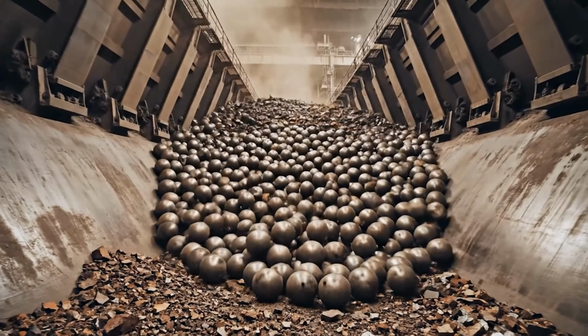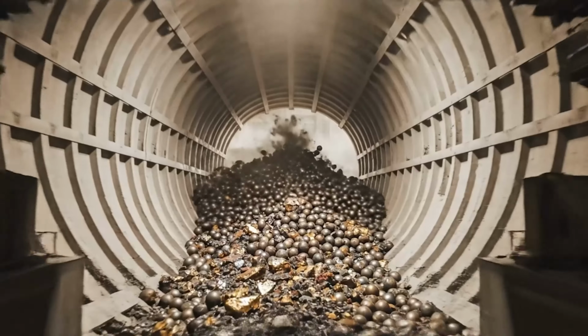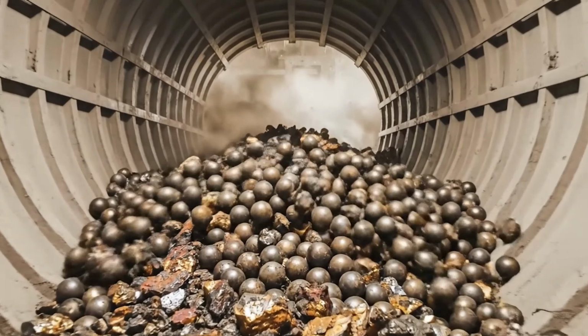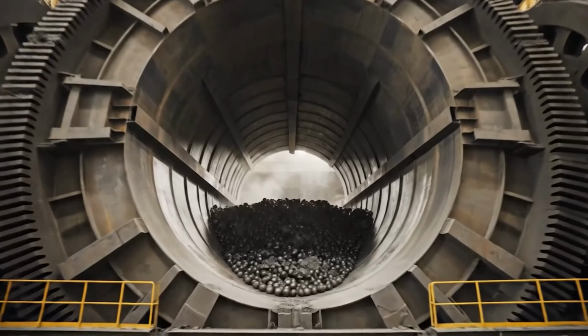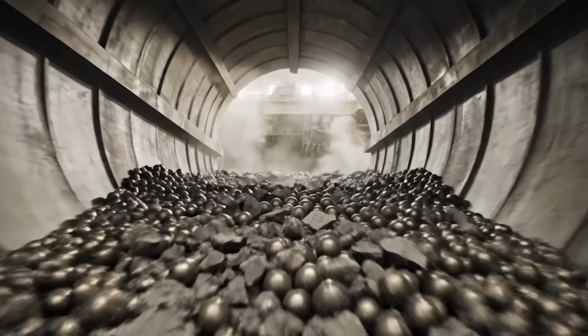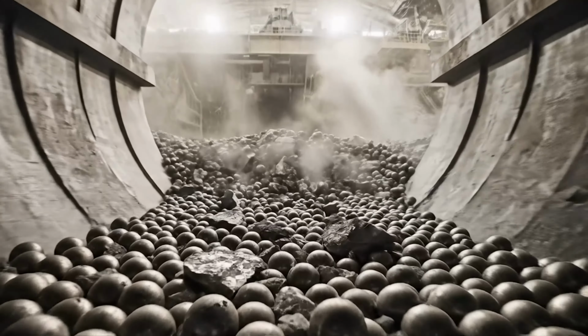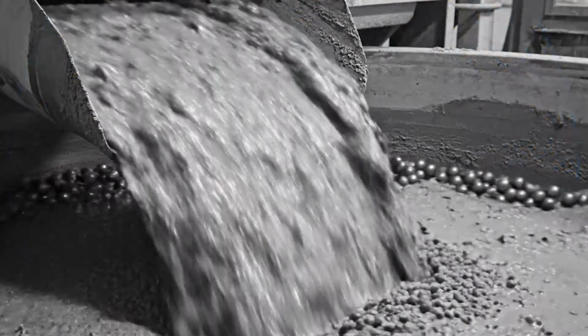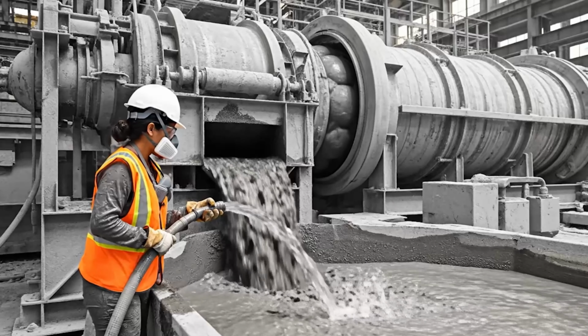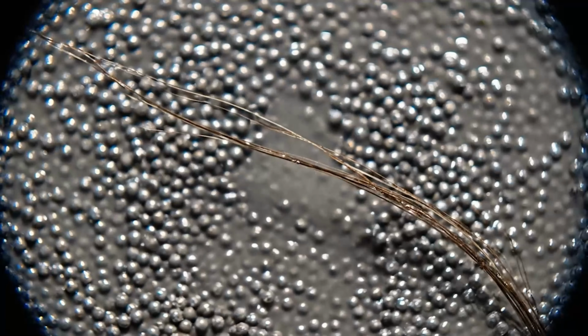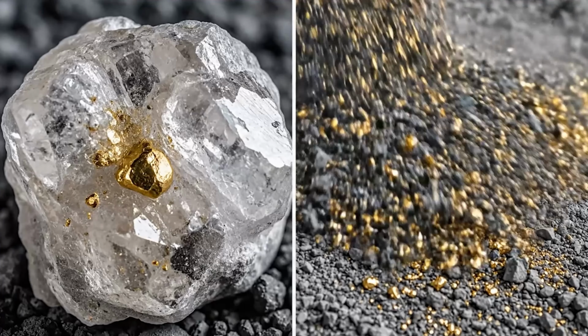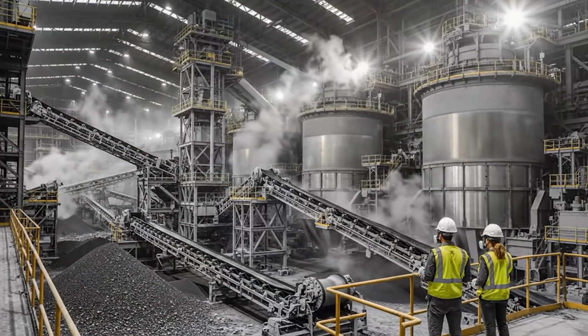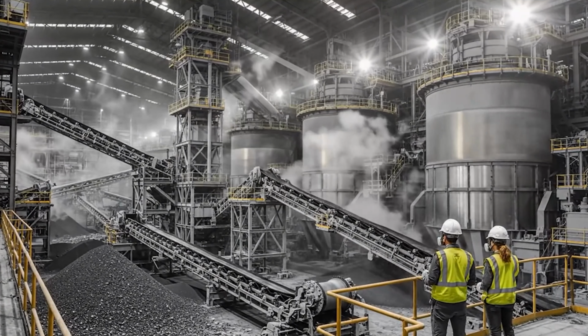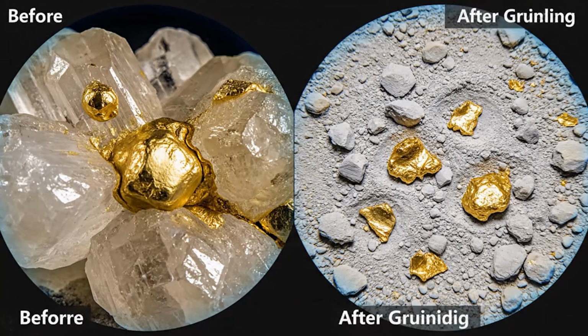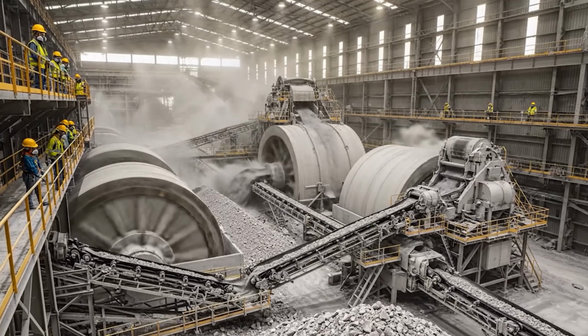The ore goes into semi-autogenous grinding, SAG, mills. Enormous rotating drums up to 12 meters in diameter, lined with steel and partially filled with the ore itself plus steel balls. Water is added to make a slurry, and as the mill spins for hours, the rock is pulverized to particles finer than 100 microns, about the thickness of a human hair. This fine grinding is crucial. It liberates the tiny gold grains trapped inside quartz or sulfide minerals. A single large mill can process 100,000 tons of ore per day.